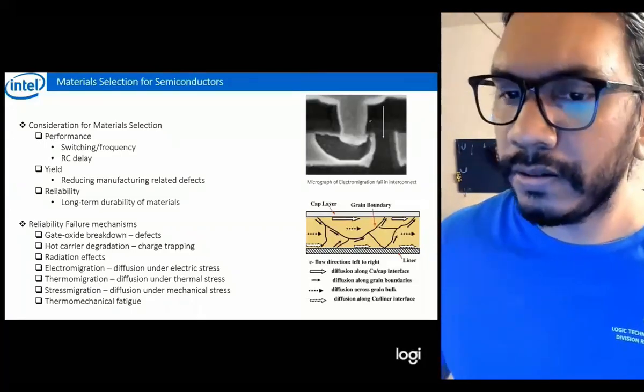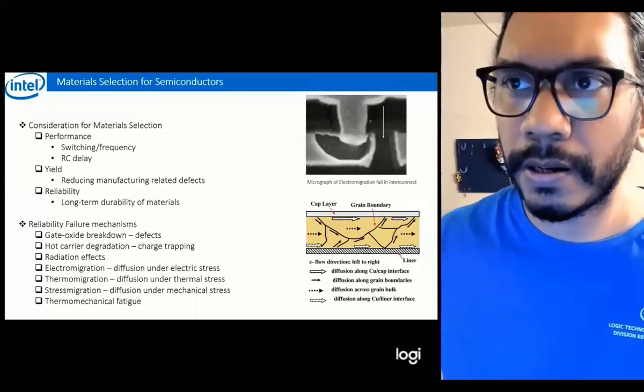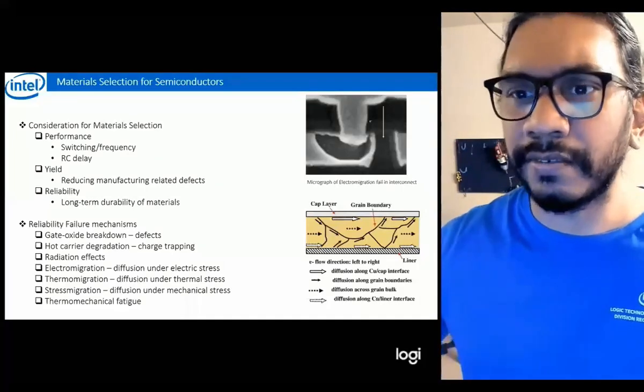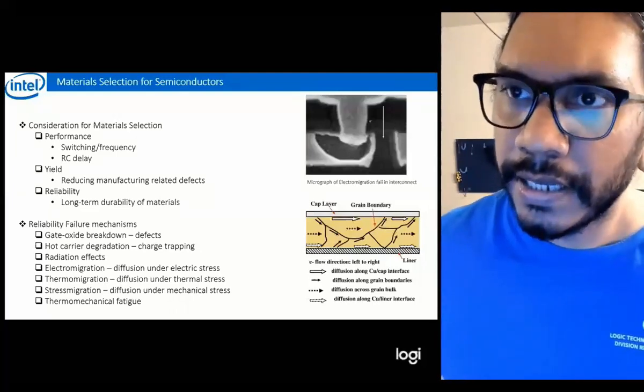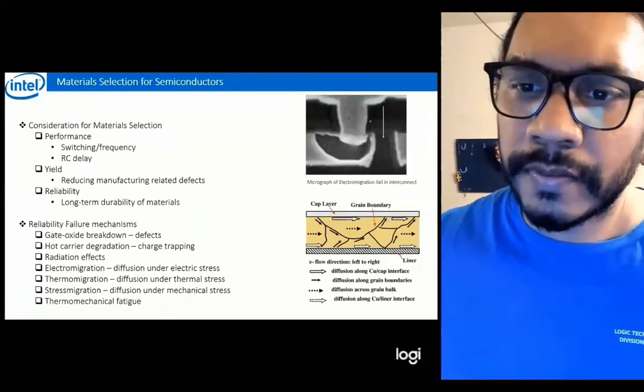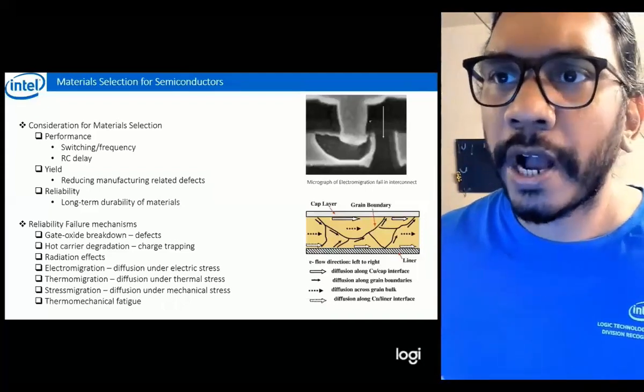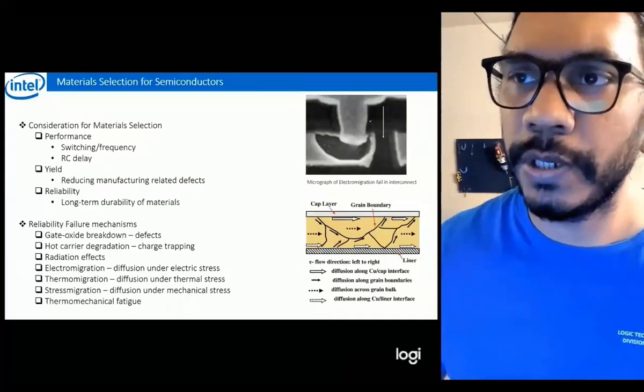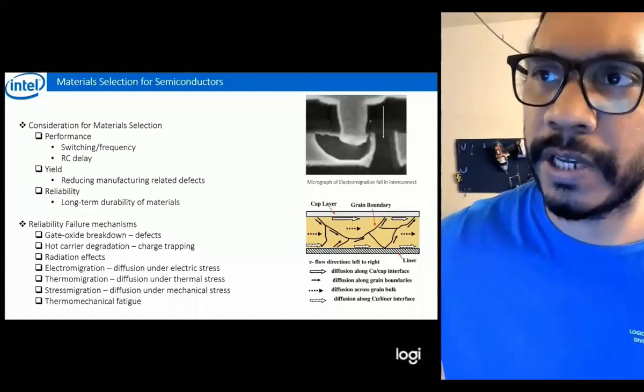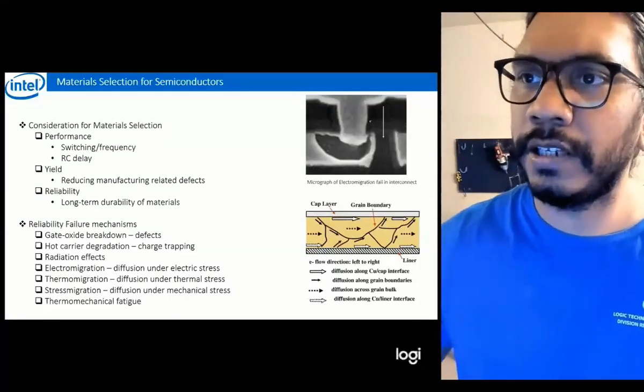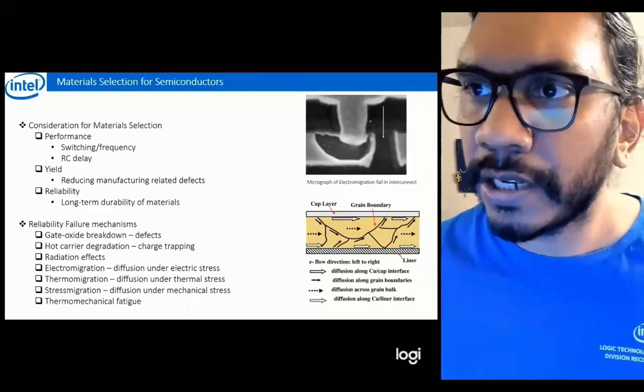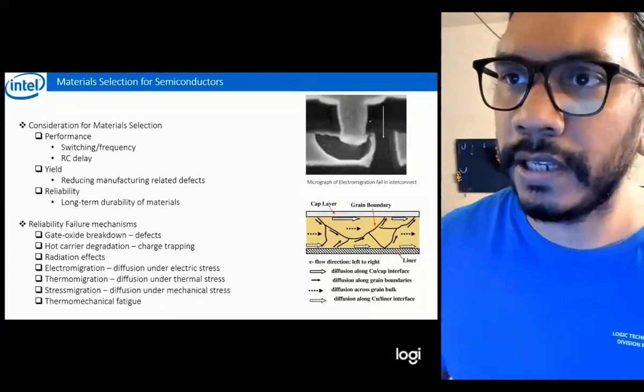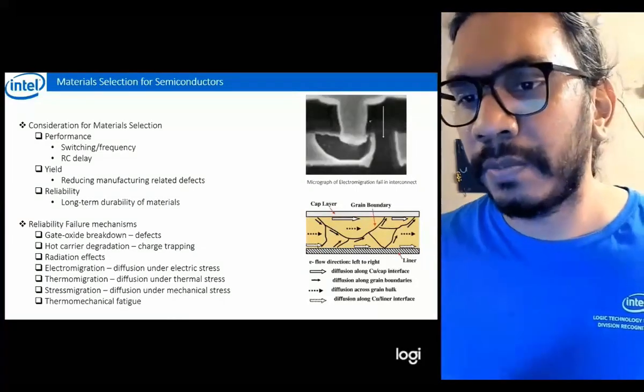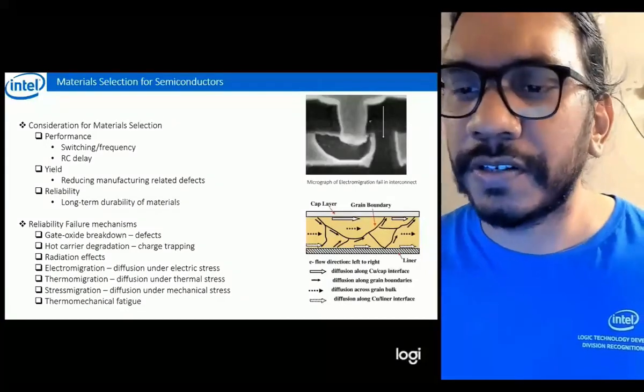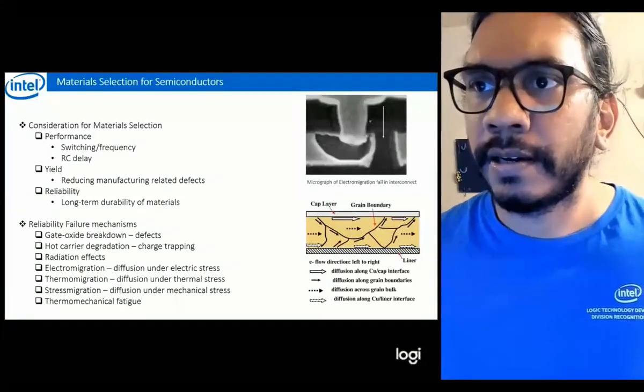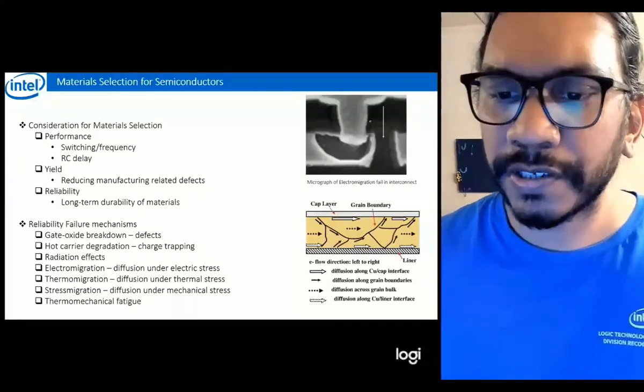So the way we test this is we do accelerated life testing. We increase the temperature, increase the currents, and from the know-how that we have, from the equations that we know, the temperature dependence of the time to failure and the stress dependence of time to failure, we can back calculate the lifetime as if the computer was running at the use condition, which is usually a smaller temperature, smaller stress current, and things like that.